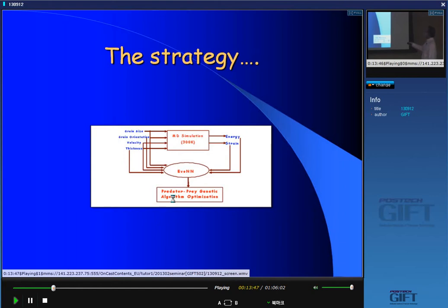We'll do that. While we are doing that, these are the variables. Any metallic assembly will have a grain. So grain size is a parameter that will vary from material to material. In our simulation, grain size varied. Grains could be at different orientations to each other, and we can create those orientations. There are techniques of doing that. So grain orientation varies. Velocity means the velocity at which the layer tries to move. Basically, that is a measure of the shear force that you are applying. And thickness is how thick, how many atom layers are you coating. Okay? A thin layer and a thick layer may not fail in the same way. So these are my system variables. I have to play with them to come up with a certain combination of all those things which will give me the optimum property of the steel that I am looking at.